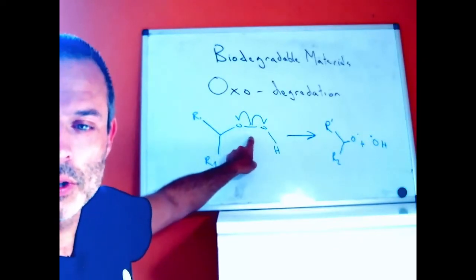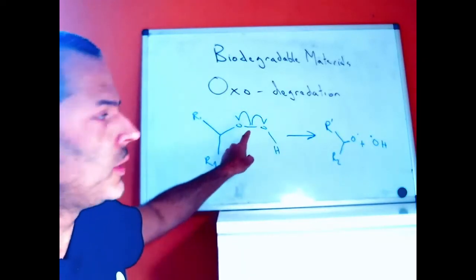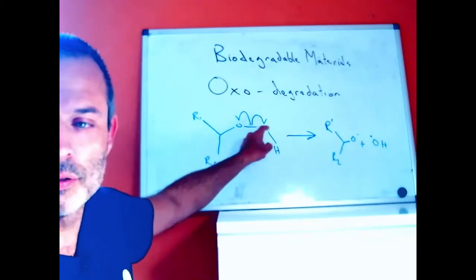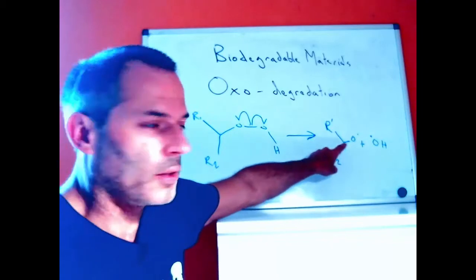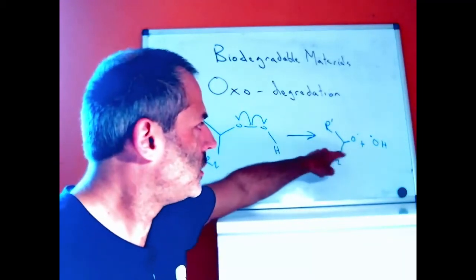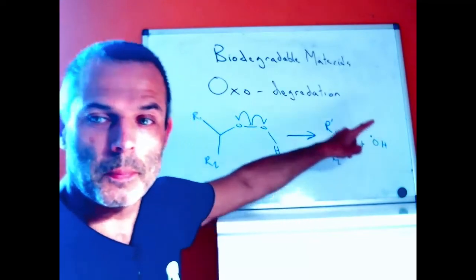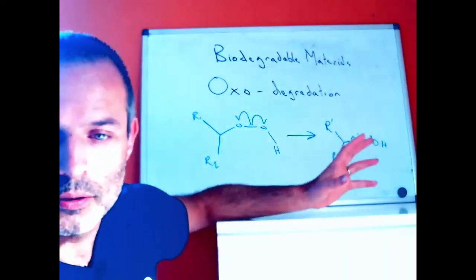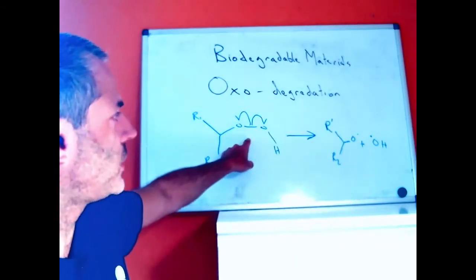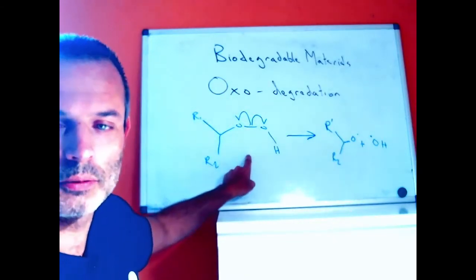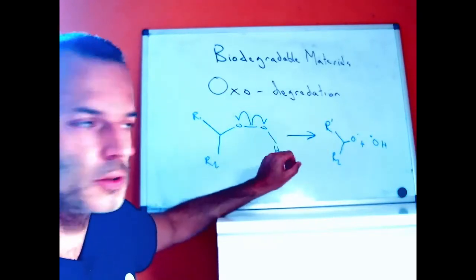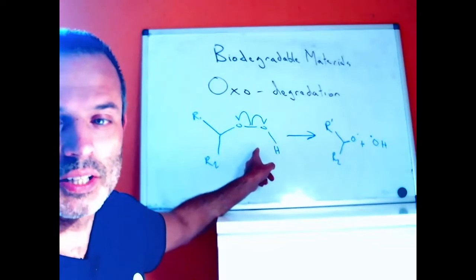And this peroxide can break down to form two radicals. This bond can break to form two radical species, the radical oxide here of the polymer and an OH radical. This is the slowest possible step in our reaction, because we're making two radicals out of an unstable, but at least reasonably stable, chemical species.